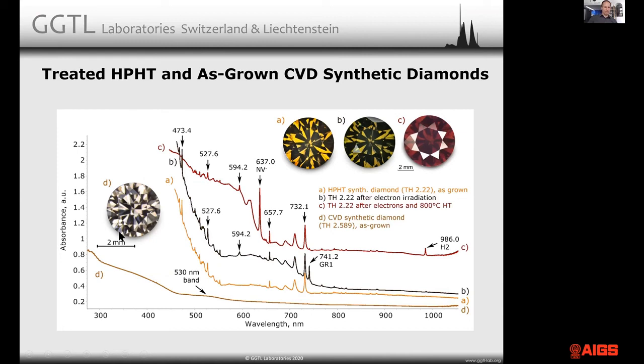That's why they basically throw them in parcels of natural diamonds, and that's how we get them here at the laboratory in the end. In HPHT synthetics, brown color can be induced by radiation. Here you see a sample. The best samples to start with are overly dark, relatively high nitrogen, and if possible high nickel containing synthetic diamonds. You irradiate a stone like that, it'll basically turn brown.